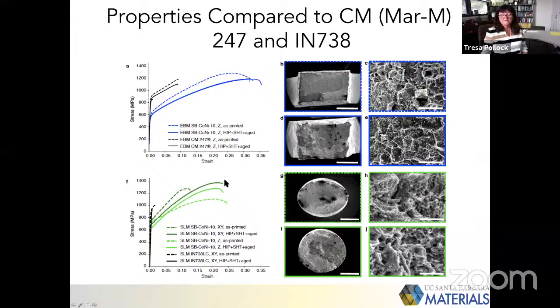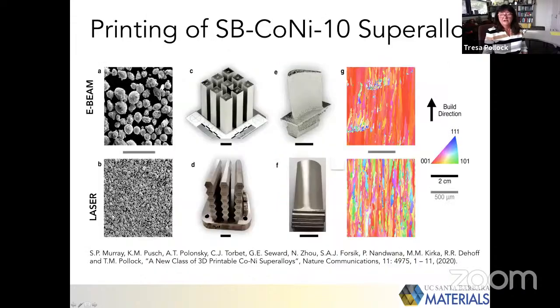And so our working hypothesis about why we're able to obtain these high ductilities in the as printed conditions really comes back to the fact that we've controlled the solidification path such that we're able to avoid cracking in the liquid state, as well as in the subsequent cooling down through the solvus down to room temperature.